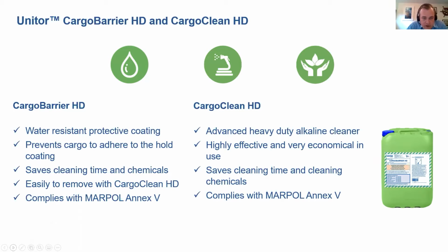Our latest products, newly launched last year, are Cargo Barrier HD and Cargo Clean HD. Here, Cargo Barrier HD is a water-resistant temporary coating that goes on top of the hold coating and acts as a barrier between the coating and the cargo. So that will help if you have a corrosive cargo, but it also helps for the cleaning afterwards, because if you use Cargo Clean HD in a 10% dilution, you can easily remove the cargo barrier coating, including the contaminants that stick on top of the coating.